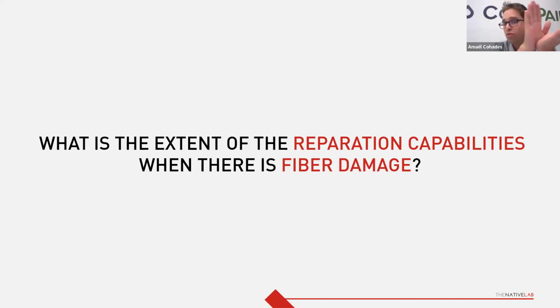Then if it's open into two, no, we cannot do anything there without adding any pressure. And most of the time, if it's open into two, it means that there is a fiber that is damaged also. And when there is fiber damage, we cannot repair. But what is interesting is that for many applications, and you see that, for example, with compression after impact testing, that is also a standard test in the composite field, where we have fiber damage for some specific conditions, and then we repair and we recover most of the properties.